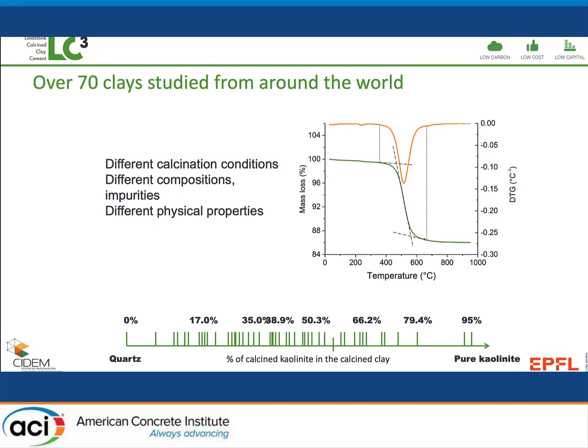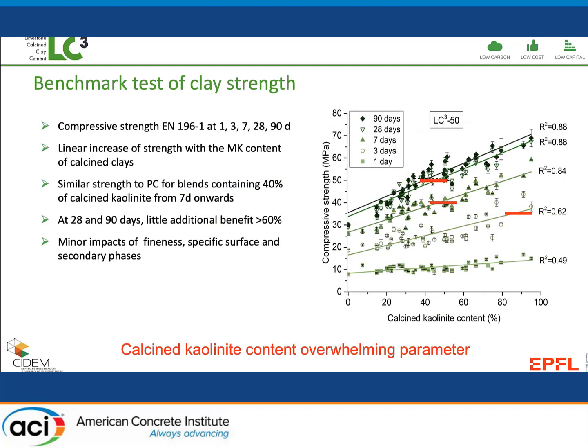And when we have studied this vast data set of clays, what we basically see is that the strength development correlates very closely with the content of the kaolinite. And these red lines on the graph here show the reference strength of the plain Portland cement. So you can see at 28 days, if you have a kaolinite content of only 40% or so, you can match the strength of your reference Portland cement.